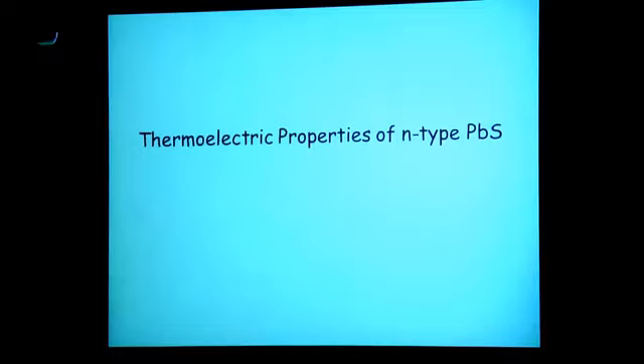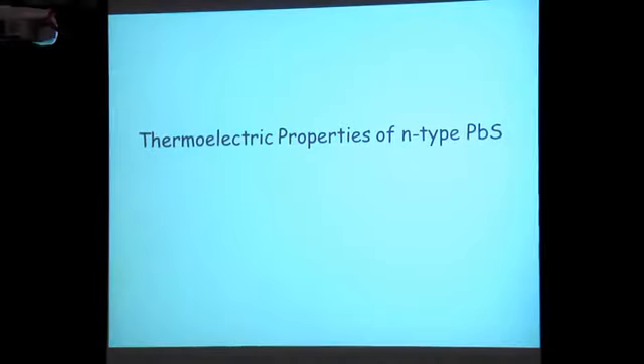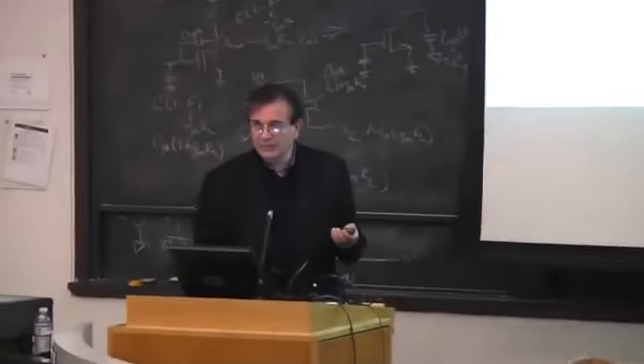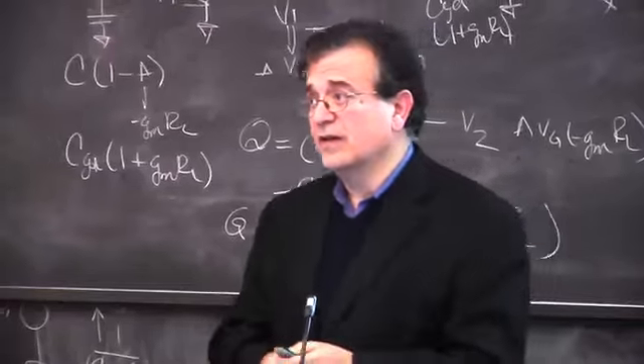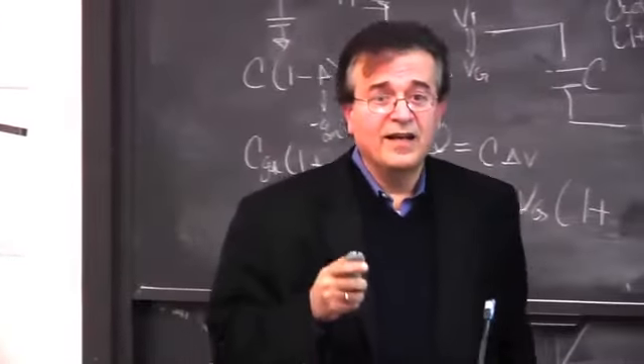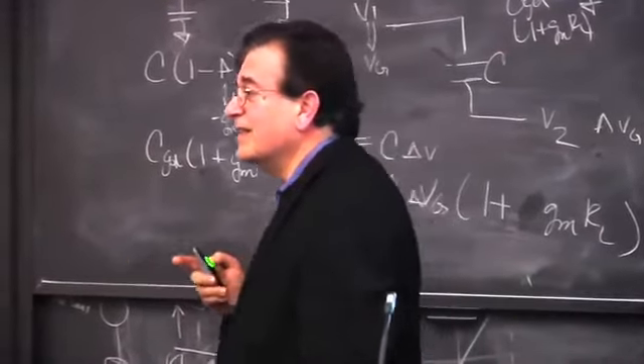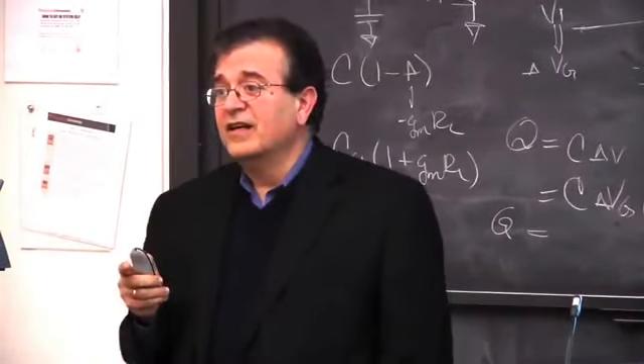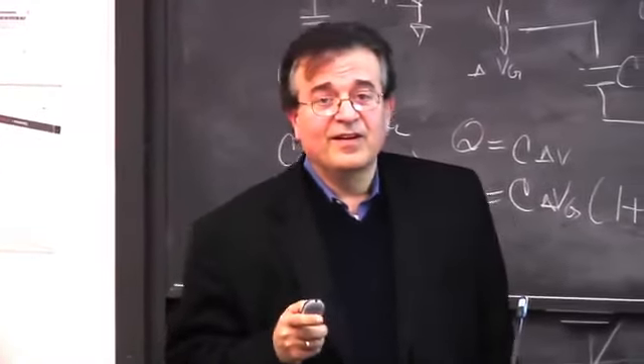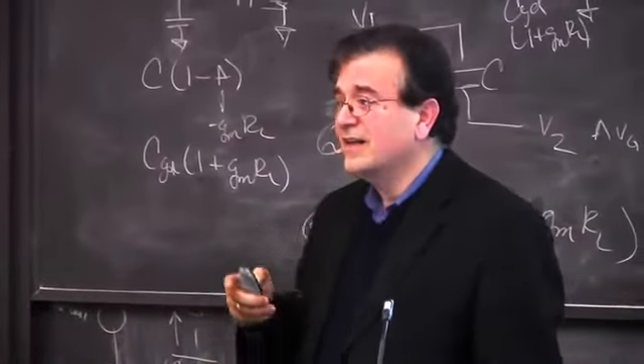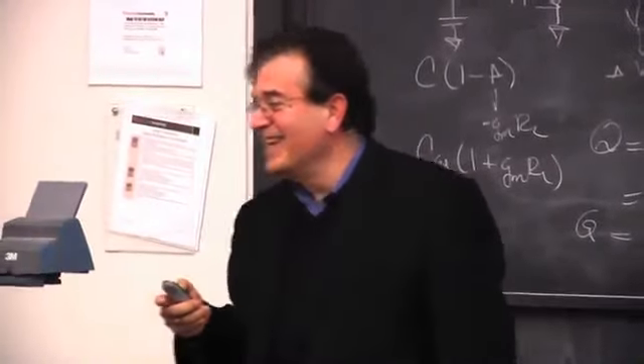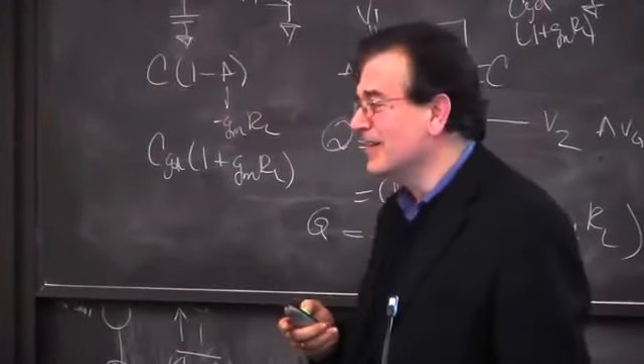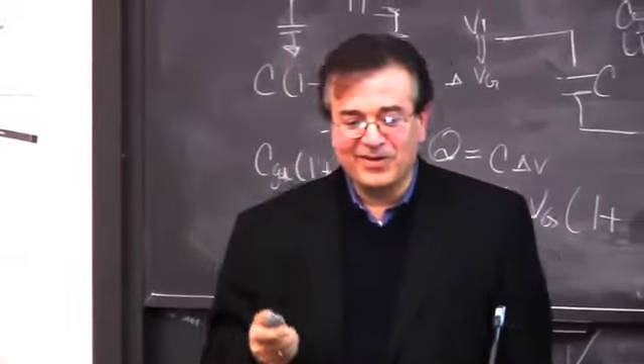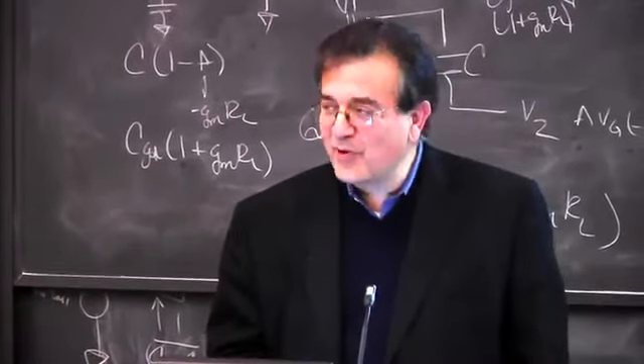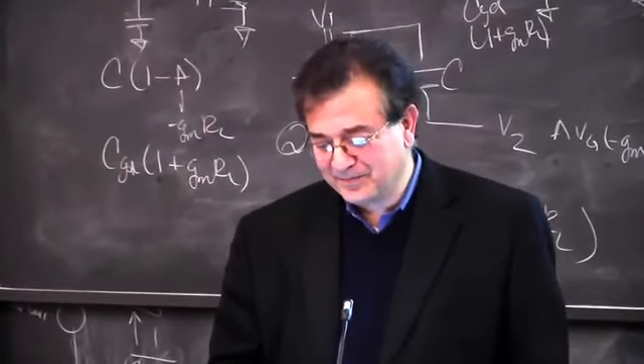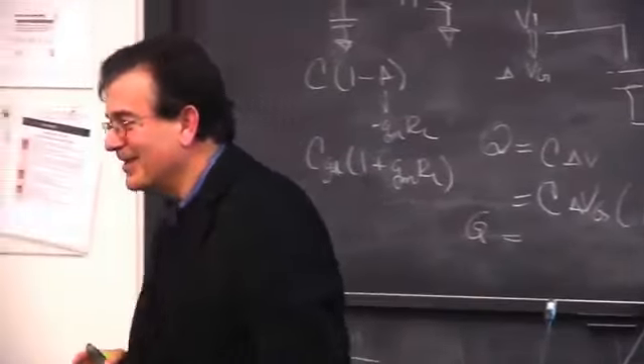But what about even simpler, even less expensive system, like sulfur? So we went to lead sulfide. Now, the Russians did a lot of work in the 50s, in the 40s in lead sulfide. They found it was good enough of a thermoelectric. They maximized the ZT to about 0.4 at high temperature. And this was good enough for the Soviet regime to put lead sulfide in its 5-year economic development plan in the late 40s so that they can electrify the Siberia. And so you can have radios and stuff like that by burning wood and things like that. It never went anywhere because 0.4 of ZT isn't high enough. But Stalin would be happy if he was alive today.